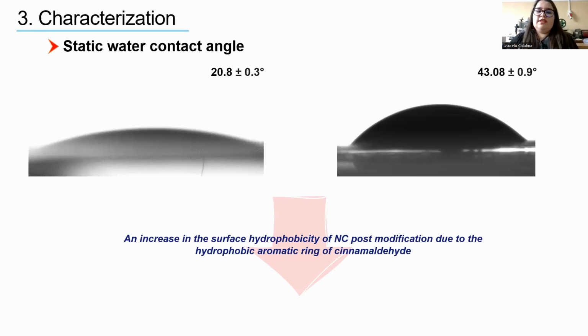The water contact angle measurement showed an increase, a doubling of the contact angle after the chemical modification of nanocellulose with cinnamaldehyde. This increase in the contact angle equates with an increase in the surface hydrophobicity of nanocellulose, which can be attributed to the new aromatic rings grafted on the surface of nanocellulose, which are known to possess hydrophobic character.